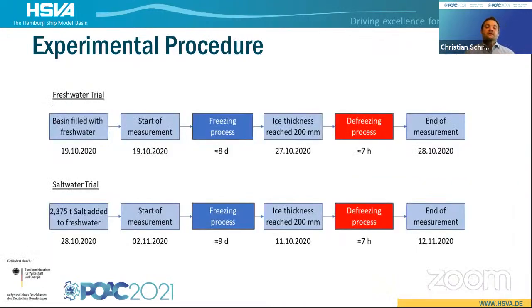How was the experimental procedure? So, of course, we first filled the basin with fresh water. In this case, we had a freezing process first to cool down the water and then to generate the ice sheet of 20 centimeters in about 8 days. And afterwards, we had a defreezing process of a bit more than 7 hours. The tank itself was relatively warm after that, but the ice itself needed a bit longer to heat through, until the forces could be measured during the measurement.